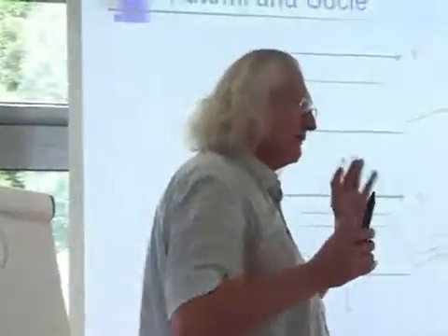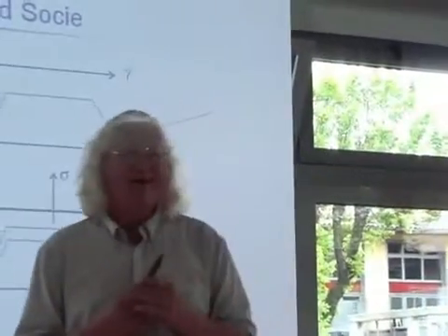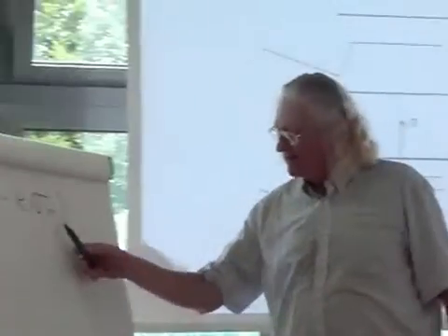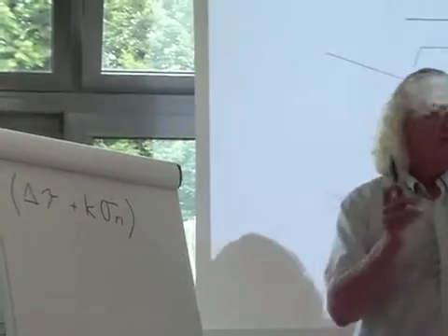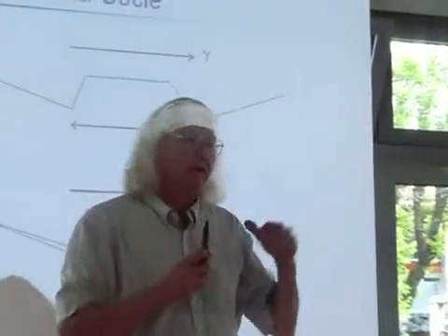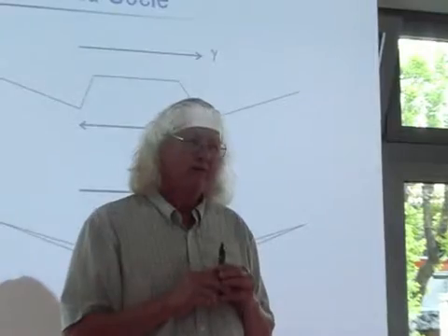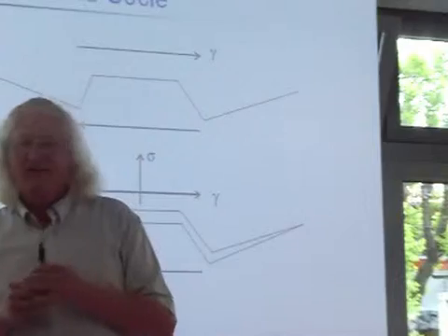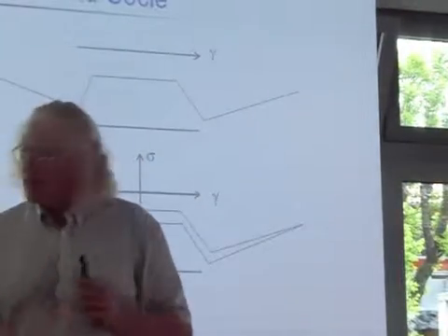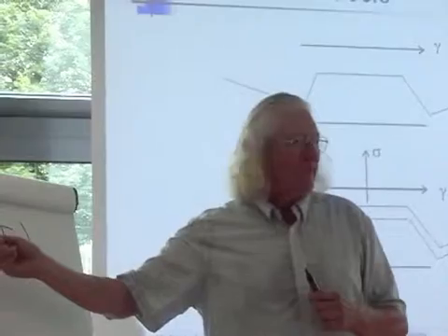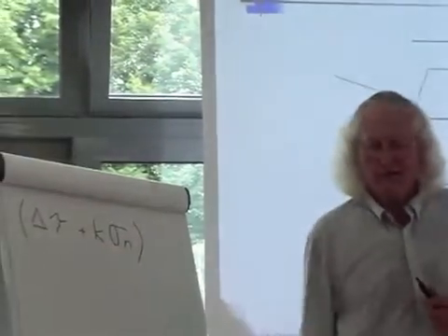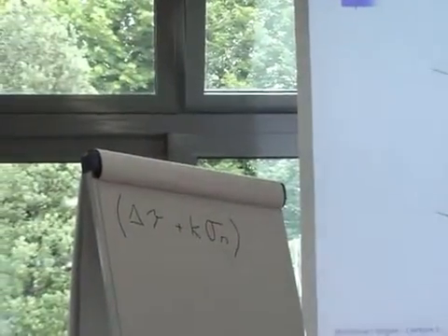So all these models really have a fundamental flaw, and it goes back to the statement I had at the beginning of this on the plane of maximum whatever. You see? It's just a problem. And Fatemi had a model that looked kind of like that. And I immediately recognized it and said, oh no. Look, you have to be sure that if there's no shear stress or shear strain, there's no damage. I said, that's what the structure of the model looks like.